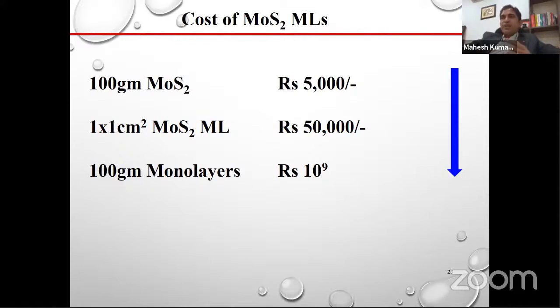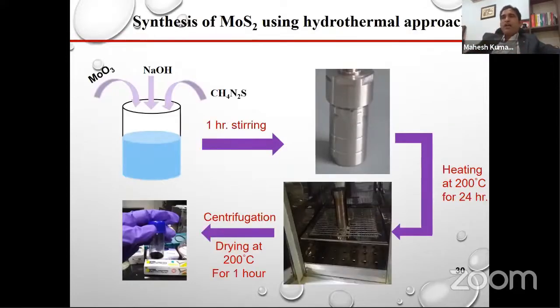At IIT Jodhpur, we are growing by chemical vapor deposition and by sputtering, but these techniques grow at high temperature. Now we have already fabricated the source and drain, so we cannot heat above 300 degrees centigrade. So we have to look for a low temperature growth technique. We have used the hydrothermal technique, with MoO3, NaOH and thiourea as precursors, which is a standard method. And finally we got this black powder.